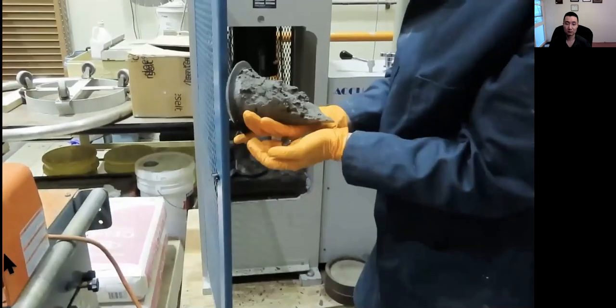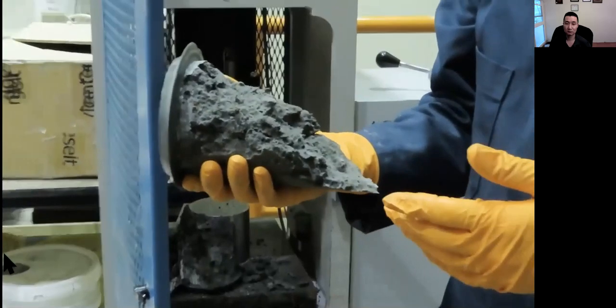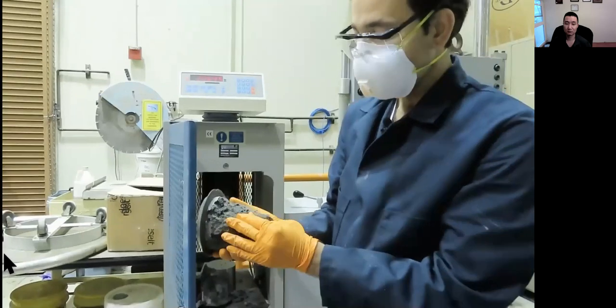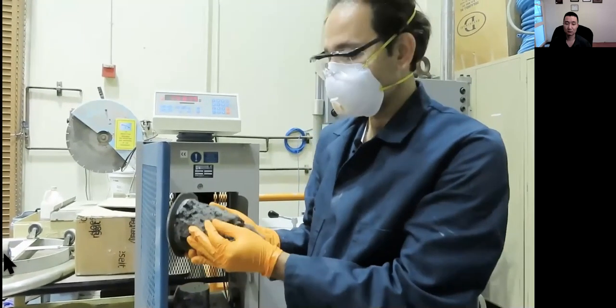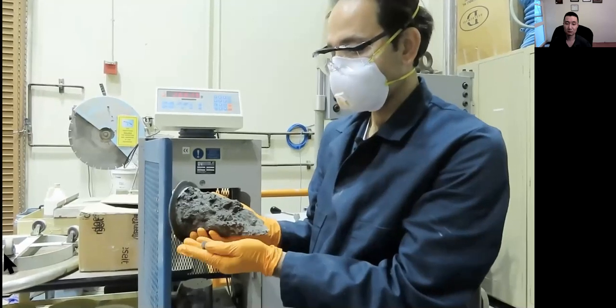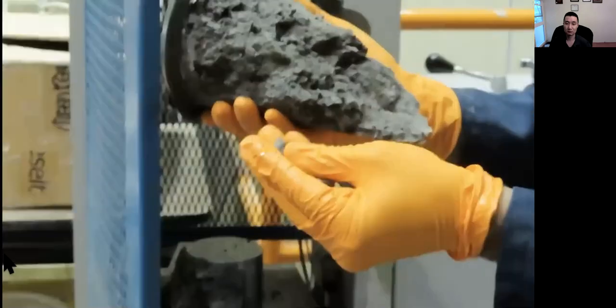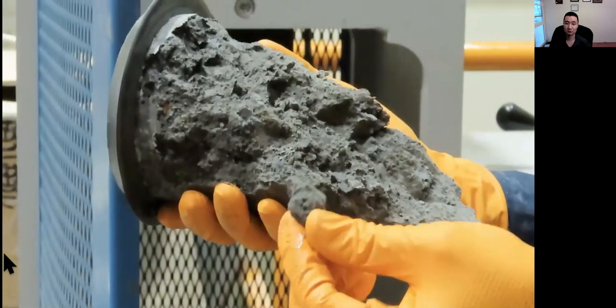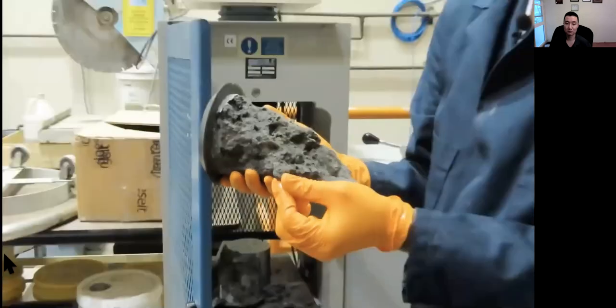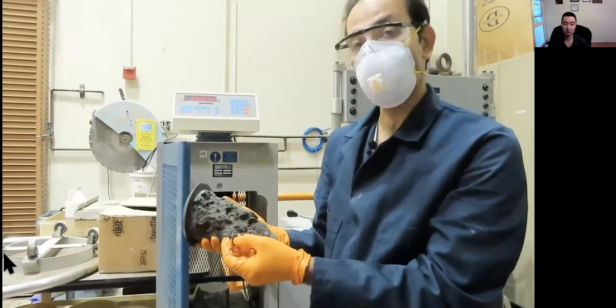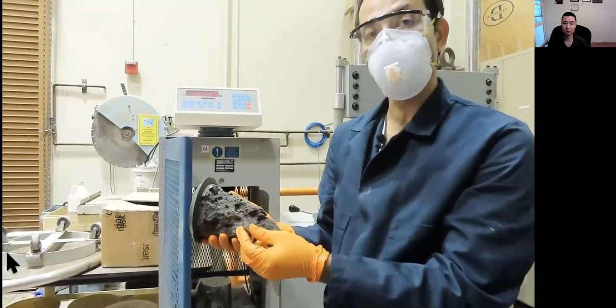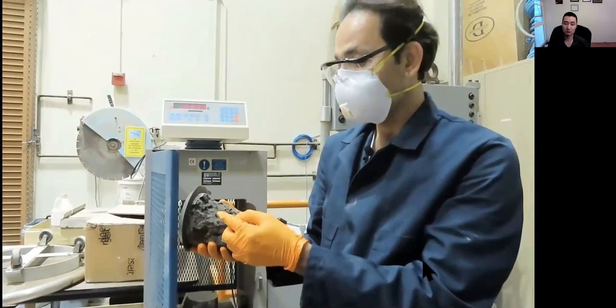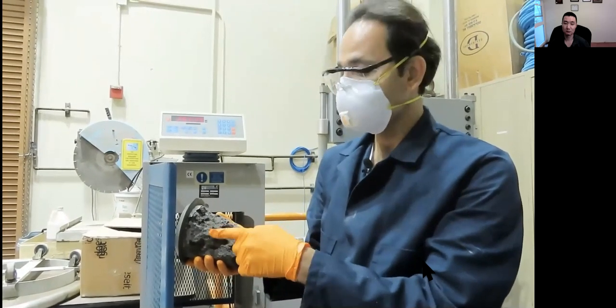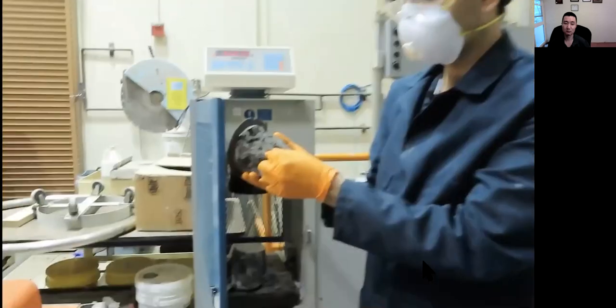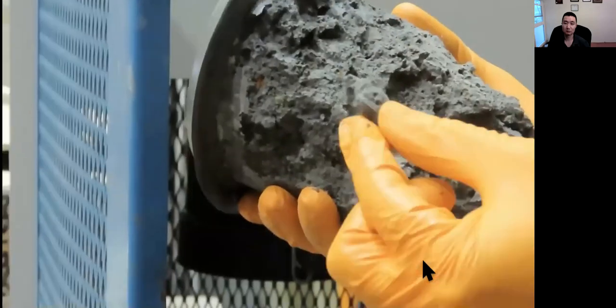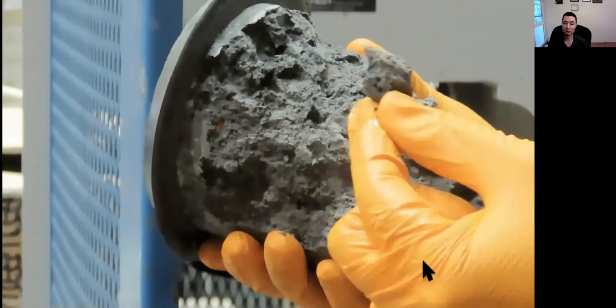For normal concrete without silica fume or superplasticizer, something like this, the paste is not that strong. It means that I can take the aggregate easily out of my sample. It means that in this case, if I increase the strength of my aggregates, it doesn't matter. I cannot increase the compressive strength of the concrete. If I want to increase the strength of the sample, I need to think about the paste first, because my glue was not that strong. I could detach the aggregate particle easily. It means that stronger aggregate cannot help me.